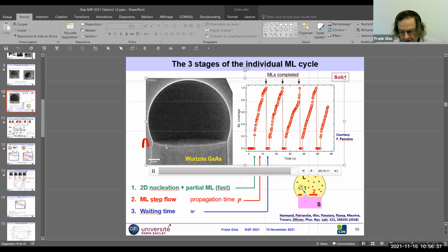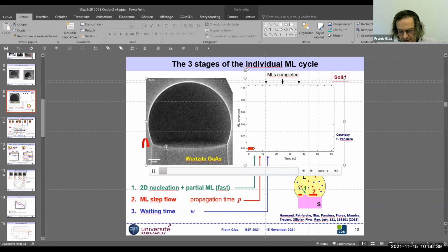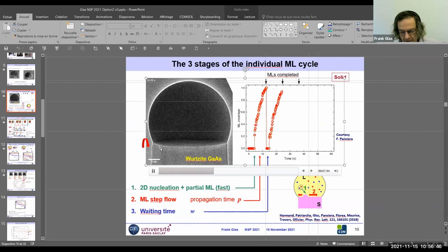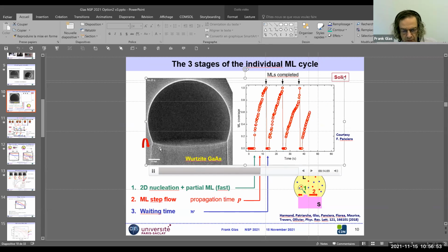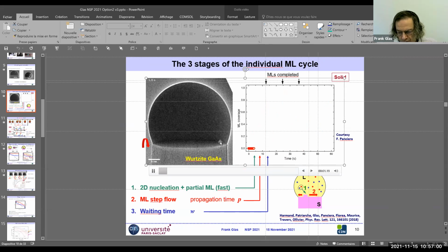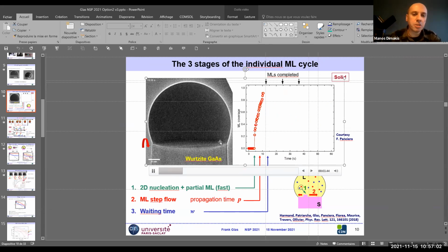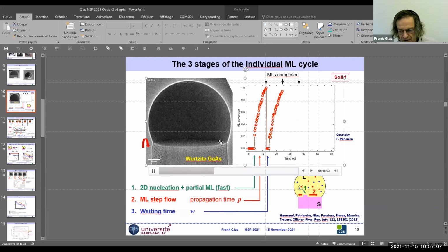So I cannot give you a perfectly 100% answer, but at least from the elements that we have, from the experiments, the rough estimates, and from what we started modeling, I believe that this can be enough to ensure the growth of a full monolayer. Okay, thank you. Of course, maybe it has to be qualified depending on the growth conditions, and so this has to be studied in more detail. Okay, thank you.